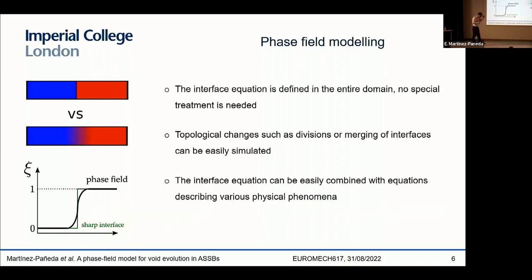And there are multiple advantages to it. Three that I like to list as usual: one is that the interface equation is defined in the entire domain, so there's no need for any special treatment. A second one is that topological changes, such as division or merging of interfaces, can be naturally captured. So you can capture how those voids will merge or divide without any ad hoc criteria. And the third one is that the interface equation can be easily combined with equations describing other physical phenomena. So it's a method that is very well suited for multiphysics problems.